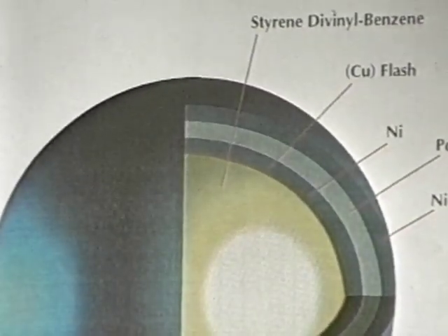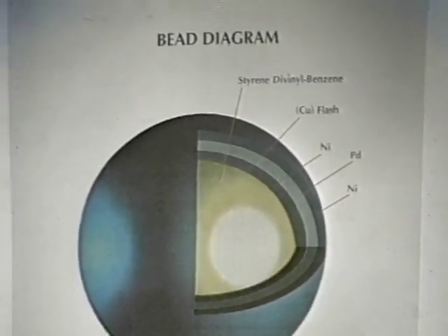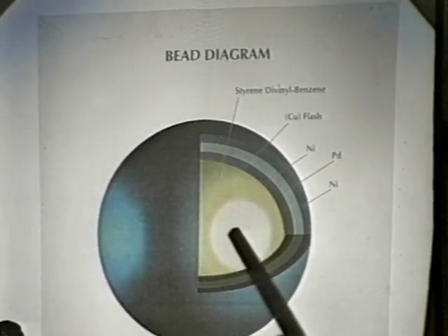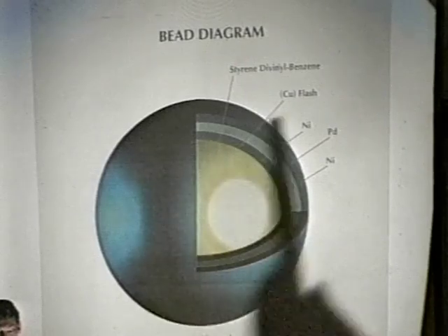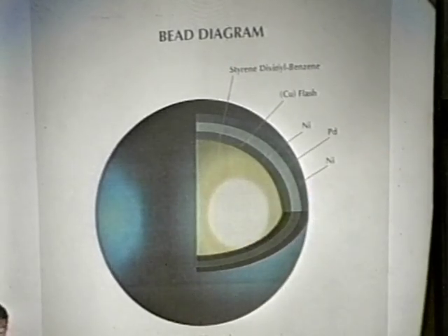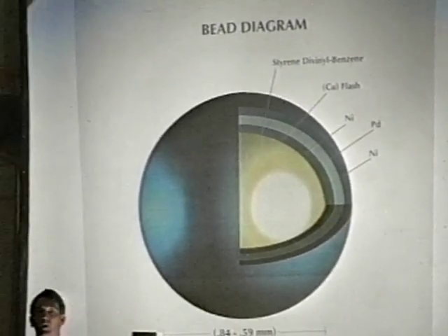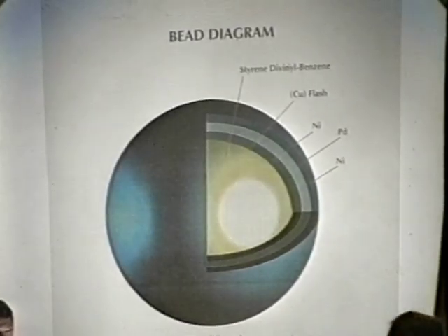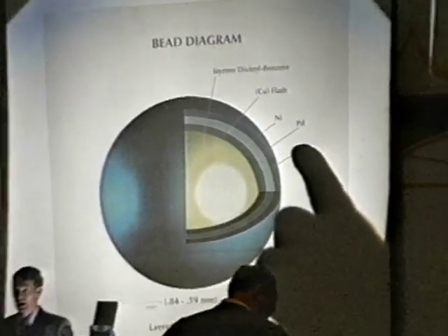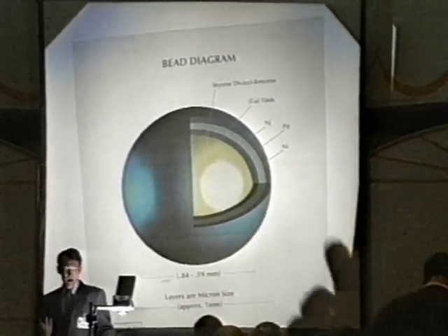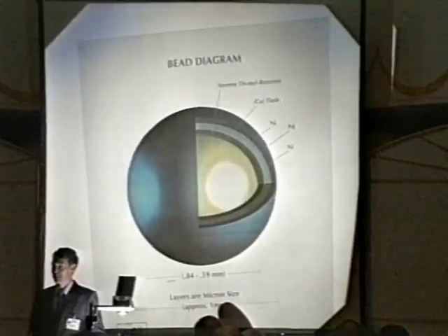These Patterson energy cells are different in the cathode design. The cathode is a structured bead system. What it amounts to is you've got a styrene copolymer, which is almost a millimeter in diameter, 0.8 millimeters in diameter. They then go through a series of processes, but you get a nickel-palladium-nickel surface on the outside of this bead, about 2 microns or so thick. So it's a bead structure which allows us to have a very large surface area. The beads themselves look like this.